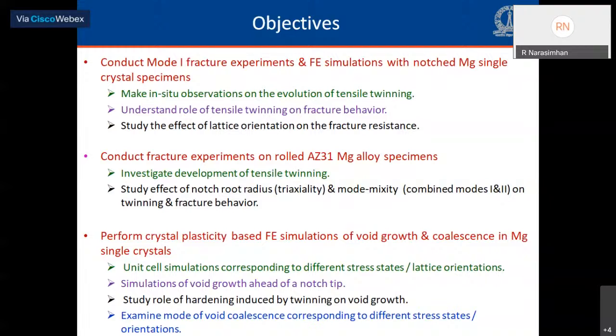The reason why we chose magnesium single crystals is because it's easy to vary the lattice orientation and understand the effect of individual twin and slip systems more easily when you work with single crystal specimens. Next objective was to look at a polycrystalline AZ31 magnesium alloy, a very commonly used wrought alloy. And again, here the effect of notch root radius, namely the stress triaxiality, and mode mixity, that is combination of the tensile mode, mode 1 of fracture, and the in-plane shearing mode, mode 2, on twinning development and fracture behavior was to be investigated.